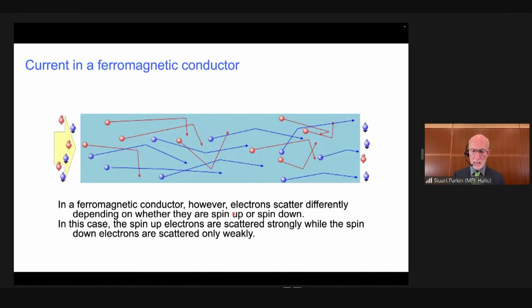Let's take a different example. In this example, the material is no longer non-magnetic. This is a magnetic material. At room temperature, this could be iron, could be cobalt, it could be nickel, or it could be some combination of those materials. When we introduce current from a battery on the left-hand side, then the current will, within a few scattering lengths of the electrons, become spin polarized. That means the current will be carried predominantly by electrons of one spin orientation. So let's say in this material, let's color code it blue. The magnetization points to your right, and the electrical current now will be carried predominantly by electrons whose spins are oriented in the blue direction, parallel to the magnetic moment of the material.